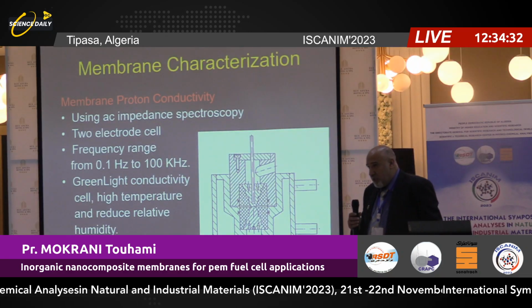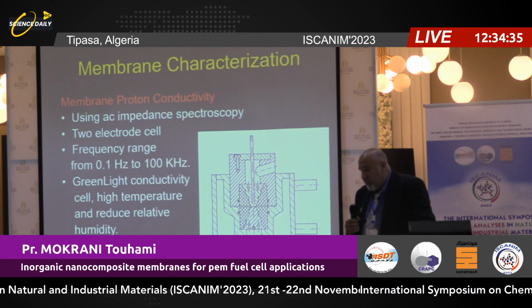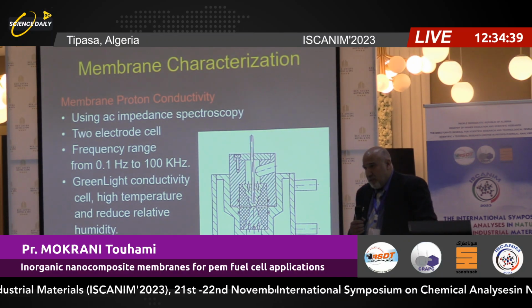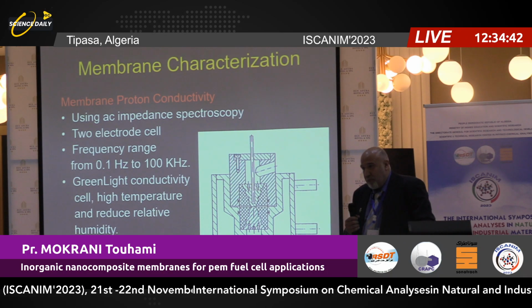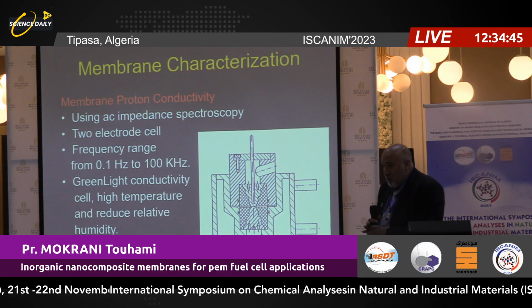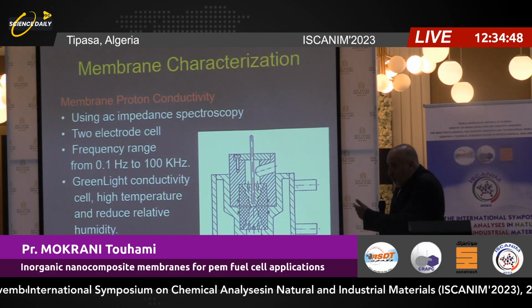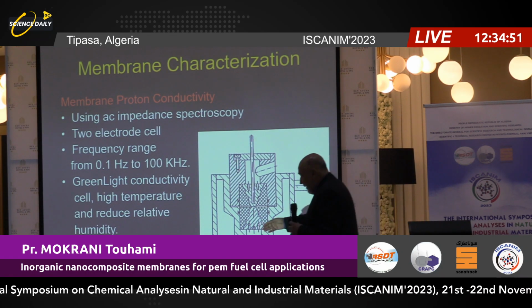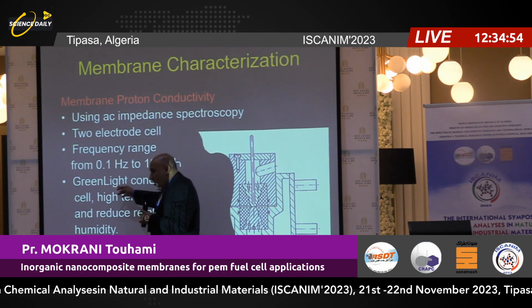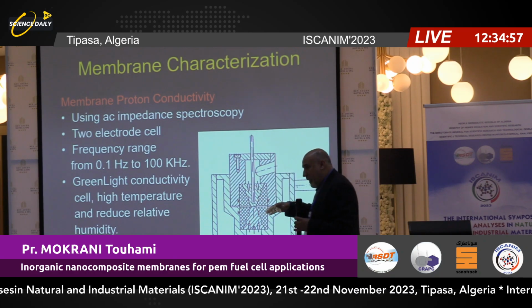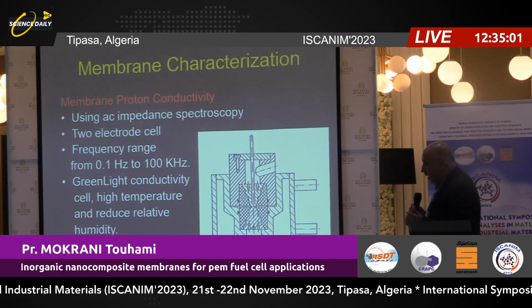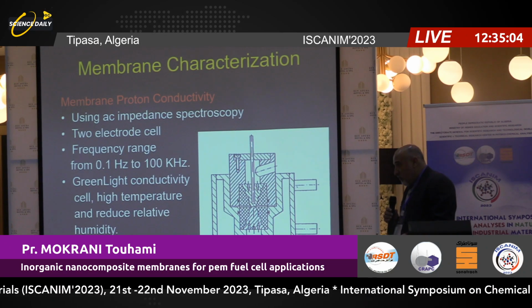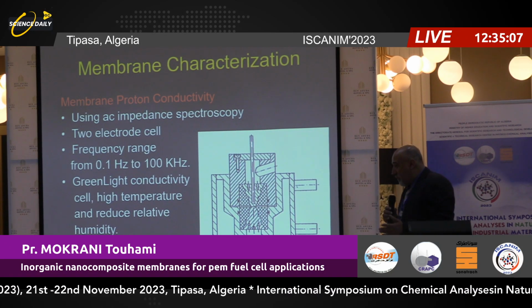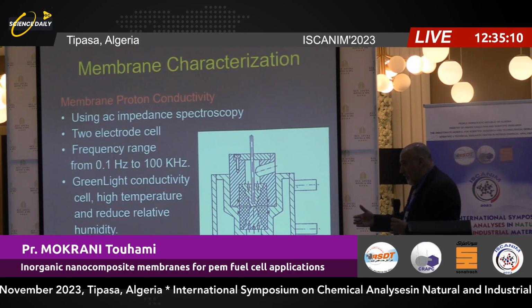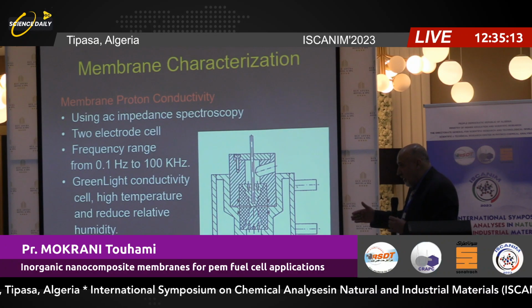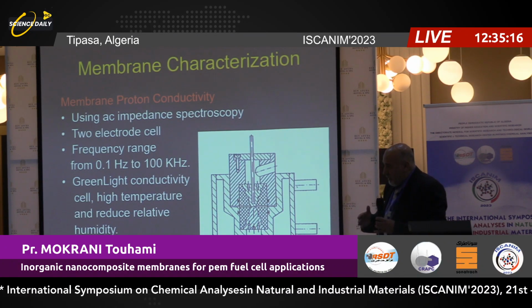So I want to speak about something which is different. It's a membrane we didn't publish about, but we are going to continue because I like this type of membrane, it's new. The main importance for a fuel cell is proton conductivity. Now we have this equipment from GreenLight, which can measure the proton conductivity at high temperature, up to 200 degrees, and reduced relative humidity. We can go from 0 to 100% humidity. The lower the humidity the better. The higher the temperature the better. Because the catalysts work very nicely at high temperature.